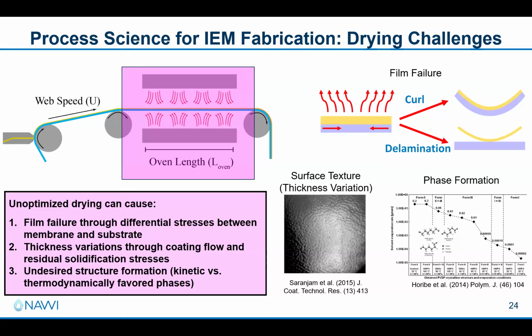And this stress development can lead to a variety of different kinds of defects, ranging from curl and delamination to small-scale millimeter or micron-scale defects like surface texturing, like orange peel. So you can form a texture that is actually like the outside of an orange, or you can get different phase formation, like what you might see for PVDF separators in batteries, where different crystal structures can form.